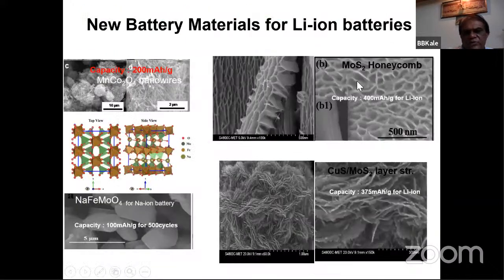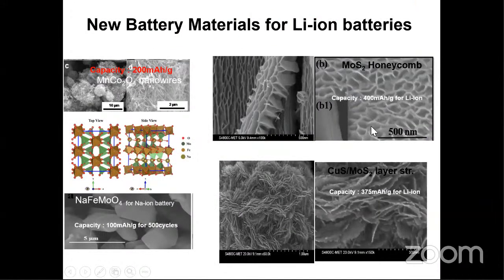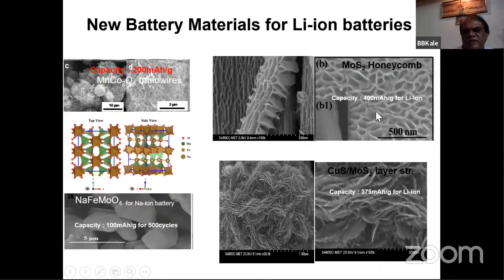This is the MoS2 honeycomb-like structure. This lithium ion shows 400 milliampere hours per gram, which is a good capacity as an anode. Now we are making the full cells. We have not made full cells; we have made half cells. We did the standardization with lithium foil. Now, instead of lithium foil, we can use any lithium cathode like lithium cobalt oxide with this MoS2 together and see the performance. So even if it comes down to 200, that is fine.